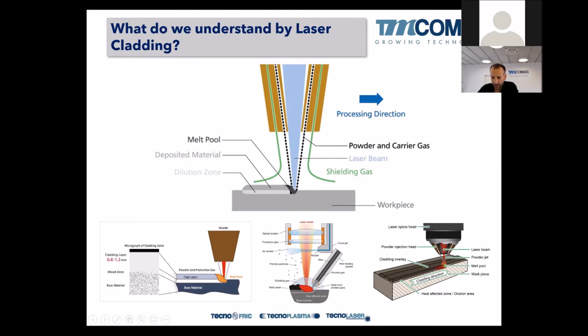So at the end we have a melt pool here, and then the cladding head will move quite fast because we have a lot of power. So the cladding speed we can achieve is up to 1.5 meters per minute. So it's quite fast. Okay, so this movement is done by a robot or by a CNC machine, and at the end we will achieve a very nice and well-positioned welding track that will cover all the repair area.